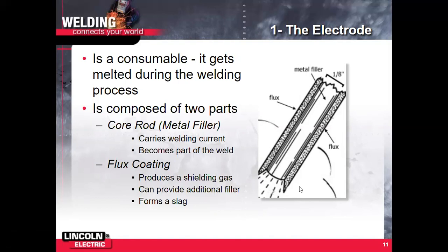So if we're talking 7024 versus 7018, the one designation on 7018 means it's an all position wire or rod. You can use it flat, horizontal, vertical, and overhead, no big deal. The 24 designation, you see that? Use it in 2 positions, flat and horizontal. In the flux of a 24 rod, you'll notice it's quite heavy and usually has a brown color to it. That's because it contains a lot of iron. That iron melts, becomes part of your weld. So that's how you make a bigger weld without having a huge core wire. You try and take that vertical or overhead, it's going to suck. I'll tell you that right now. It's not designed for it. It does not do it well, if at all. And it's just going to create mayhem and chaos.